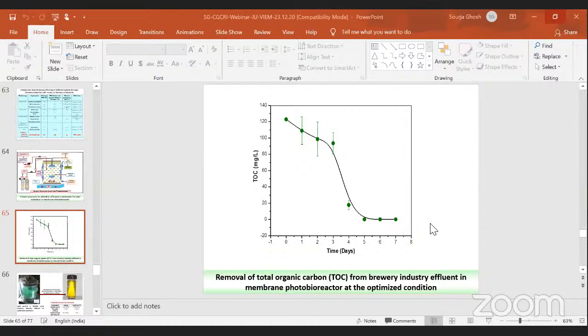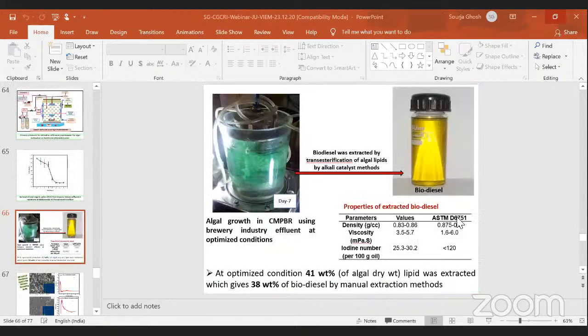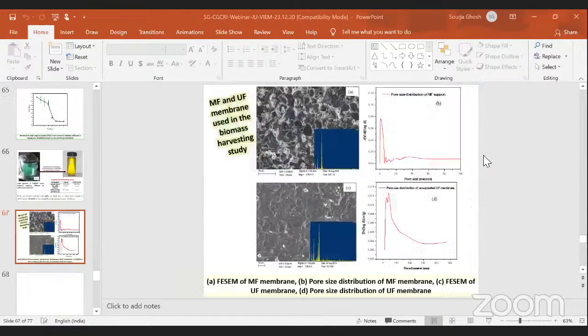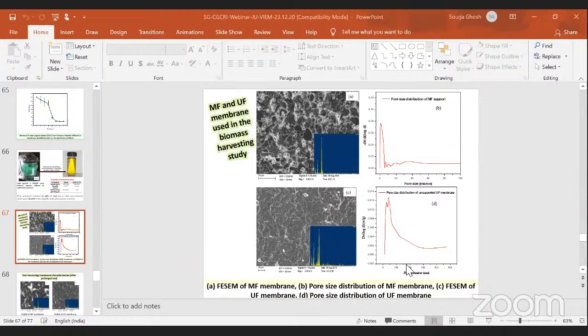This is the total organic carbon removal profile in the brewery industrial effluent during the photobioreactor process. You can see that over 120 mg per liter was initially present, and it reduces to close to zero. That is, complete TOC removal was achieved. And this is showing the biodiesel obtained from the cultivated biomass. At optimized condition, 41 weight% of algal dry weight lipid was extracted, which gives 38 weight% of biodiesel by manual extraction method, which can be increased further.